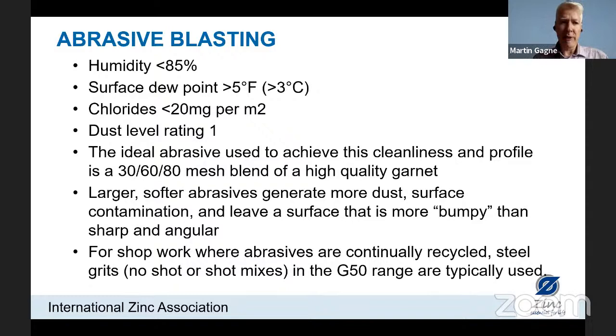Graham had mentioned dusting and also chlorides. You know, we want to clean that surface after blasting so that we have no chlorides or dust present before we encapsulate them in the zinc. Although again, the zinc will be more forgiving than a paint. So ideal abrasives are high quality garnets, and these can be mixed in a 30, 60, 80 mesh blend. Again, large softer abrasives produce a bumpy surface more than a sharp and angular surface. It may be clean, but it will not have the angular surface profile, which is important. And in the shop, where abrasives can be recycled, we have seen successful use of steel grit, although usually we prefer garnet.